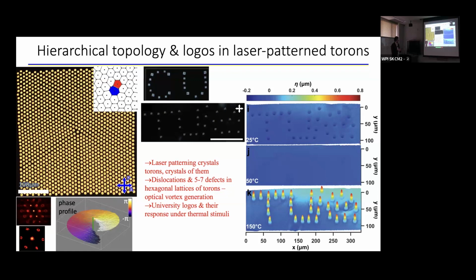It's important to understand that topological solitons are protected by topology. They cannot appear in any place effortlessly, but rather than quenching the entire sample, in which case they appear everywhere spontaneously, we can heat and quench locally in whichever place we shine the laser beam, and then we have them in well-defined positions. Moreover, at some laser power, we can pin their location so that Brownian motion will not diffuse them away. And then after this, we can shine a light appropriate for the photoinitiator at some UV wavelength, say 380 nanometers. Then we can cross-link such a sample.